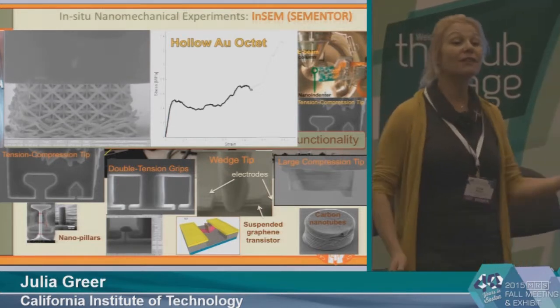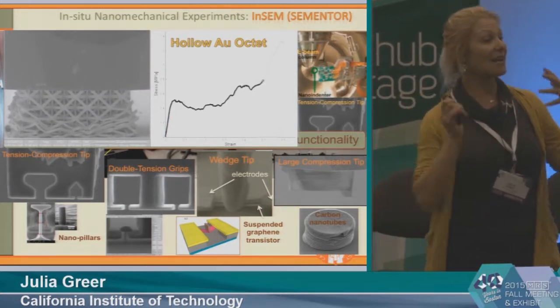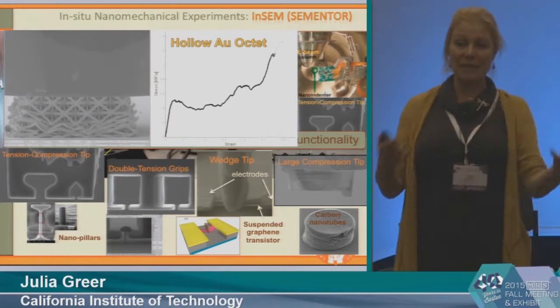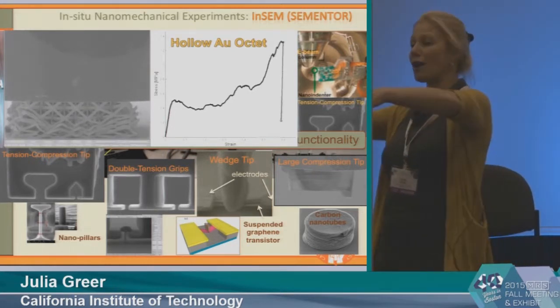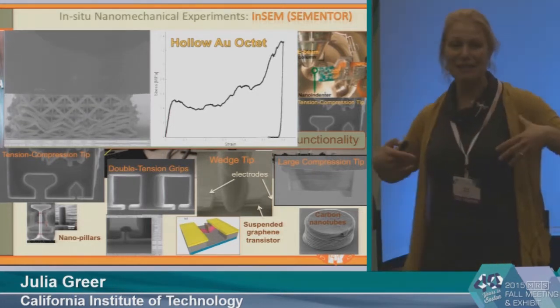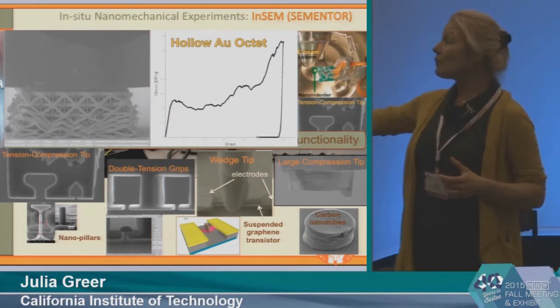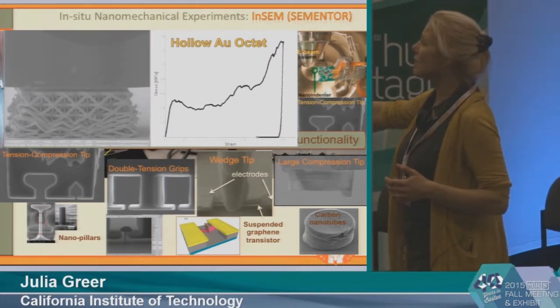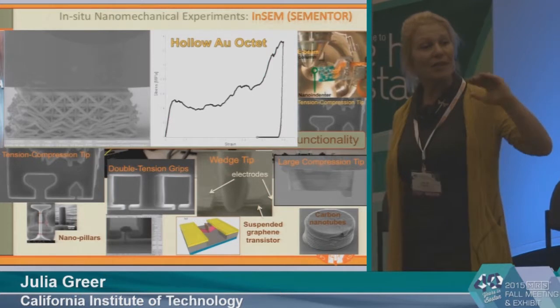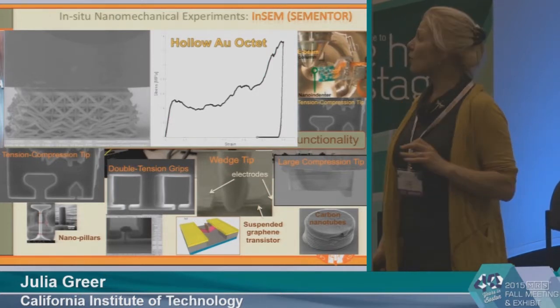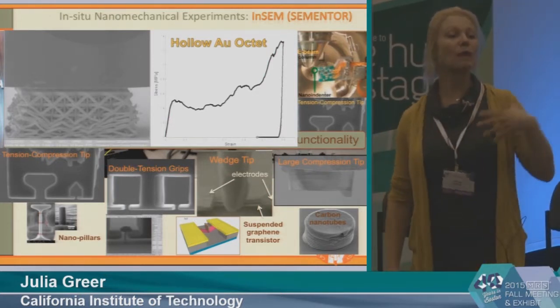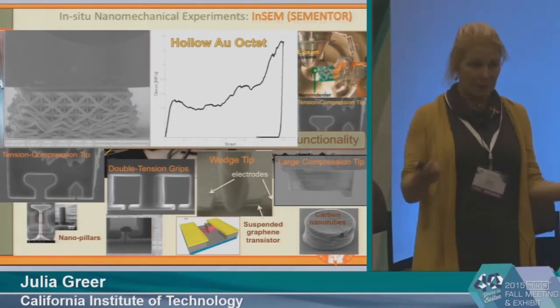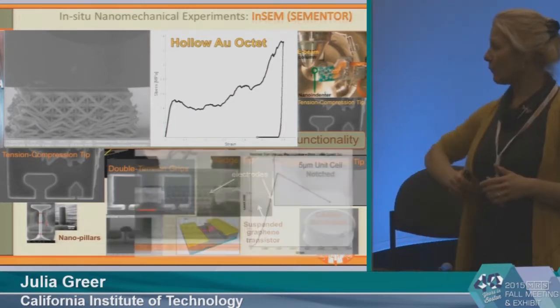So wouldn't you like to have this kind of material in your helmet or in any kind of packaging or in anything that you're trying to protect, where instead of transmitting the shock onto whatever is adjacent to it, it would take the deformation all upon itself. And what we can do is now correlate all the undulations in the stress strain data with the individual layer collapse. So this kind of technique offers us a much more complete set of information than what you would be able to get without seeing what you're doing.